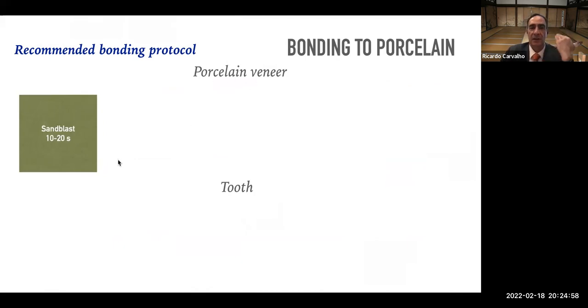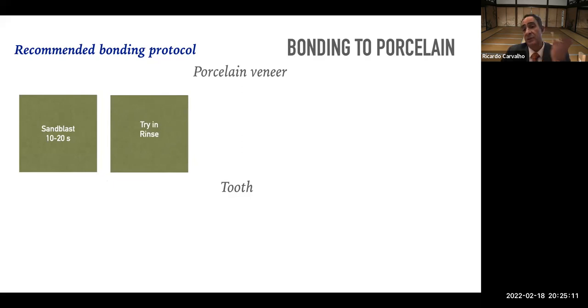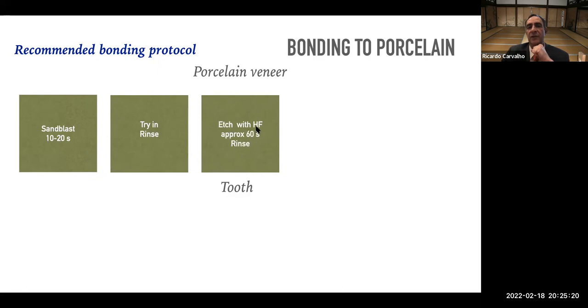Okay, very well, folks. Now we're just gonna review then the recommended bonding protocol. If we are dealing with the porcelain veneer, so I do the porcelain first, sandblast if there is a need for that. Eventually comes already blasted from the laboratory. And then what you're gonna do in your practice? Well, if it is already only sandblasted, you can just do the try-in, you can rinse, and then you go for hydrofluoric acid etching, 60 seconds, you rinse, you dry very well, you check if there is any excess etching or over etching, any whitish surface.